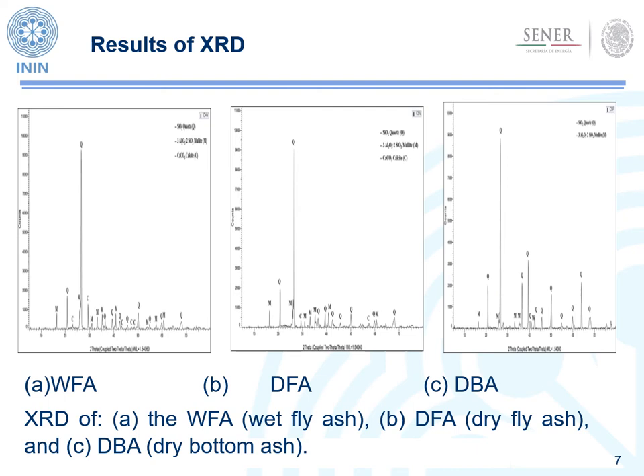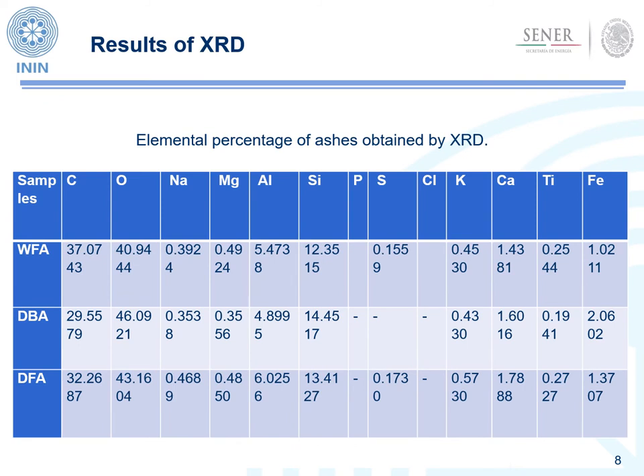X-ray diffraction lets us identify a crystalline mixture with a higher content of quartz and mullite, which indicates these are bituminous ashes, and with a lower content of calcite. We see more content of calcium and aluminum in dry fly ash samples than in the other two.